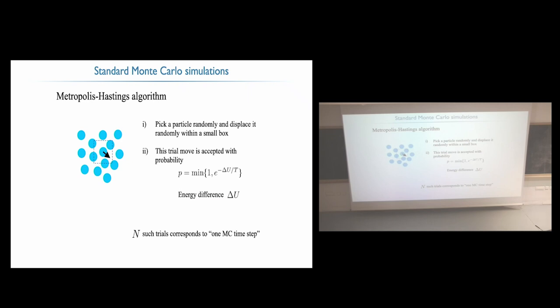And then you compute the difference in energy, delta U, before and after doing this move. And you use the Metropolis filter, so you accept or reject the move with a probability which is the minimum between 1 and exponential minus the energy difference divided by T. So let's see a bit what goes on here. If the energy decreases, the minimum is 1, so you're going to accept all the time. But if by chance, for example, this particle overlaps a bit with its neighbor, so it increases the energy, you don't reject, you accept, but just with a weight that's proportional to what you want in equilibrium, which is given by Boltzmann.